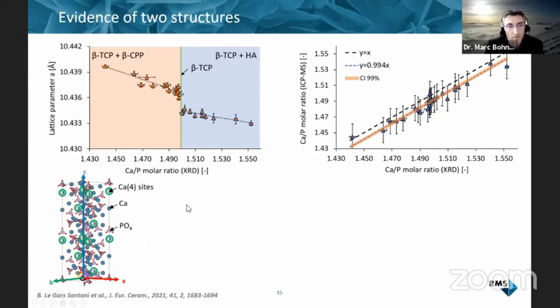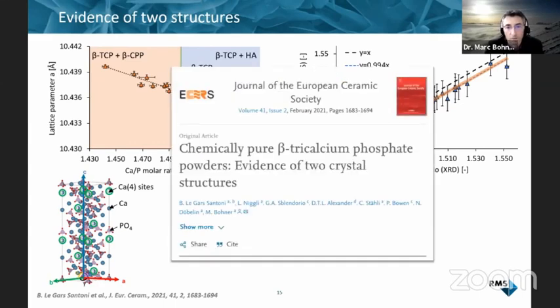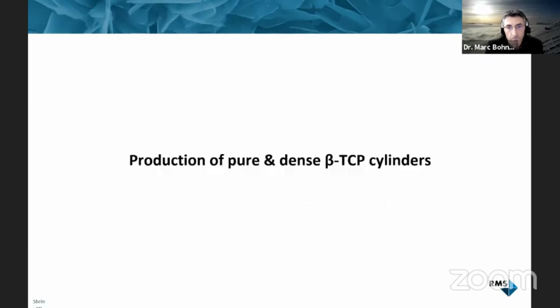The conclusion from looking at this structure and some atomistic simulation that I'm not going to show today suggests that actually we have different beta-TCP within the beta-TCP, and they just vary in the filling patterns of these calcium 4 sites. So there are some large domains in the order of 100 nanometers that have one filling pattern, and other domains that have a different filling pattern. If you want to know more, you can check this paper from the JECS early this year.